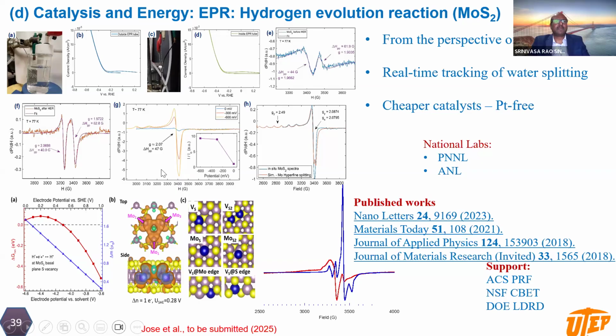Okay, so this plot shows electron spin resonance signals as we change the potential from 0 millivolt up to 600 millivolt, and you see the intensity of the signal varies strongly as a function of electric potential. So that shows that we are changing the intensity of active species which contain unpaired electron spins. Basically, the signals like this are a combination of molybdenum species as well as sulfur vacancies. So we simulated the signal and we extracted information about what exactly is going on in this in situ EPR experiment, and what are the catalytically active sites that lead to hydrogen production.